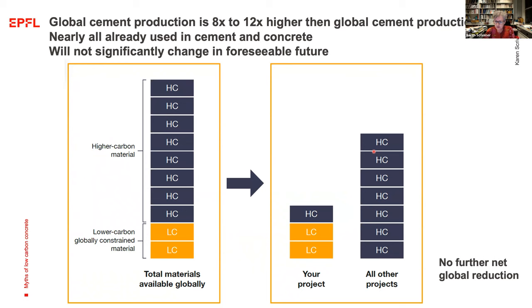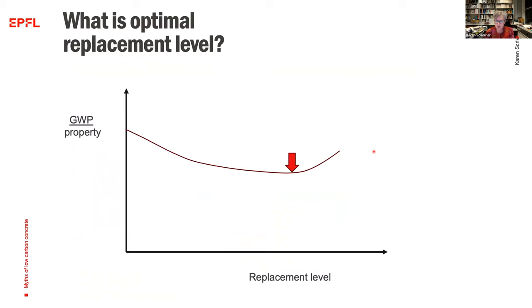And what perhaps we should focus more on is what is the most efficient use of slag. And here we can imagine to look at the amount of CO2 or global warming potential as a function of a property like strength or chloride resistance or something like that. And what we want by using slag is to decrease this, so we have less global warming potential for the concrete. And we come to a point here, shown schematically, which would be the ideal replacement level, because if we go beyond that, then because the property decreases, because, say, for example, the strength decreases, we're actually increasing global warming potential. So this is what we need to think about, and we probably need more data to really say where this level should be.